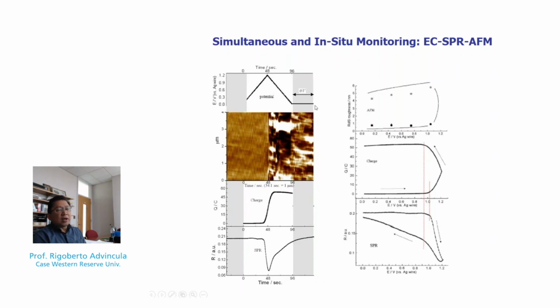And then here you can see where you actually stop the voltage injection or the electrochemistry setup, and then again you observe the morphology on one line. So this is not a spatial AFM, but this is a temporal AFM. At the same time, you can monitor the charge injected from the electrochemistry setup. And then more interestingly, you can do the reflectivity measurement as the film is deposited. So this dip in the reflectivity and the fact that we can measure the SPR indicates that we actually deposited a film that resulted in a dip in the SPR curve, because of that added dielectric material.